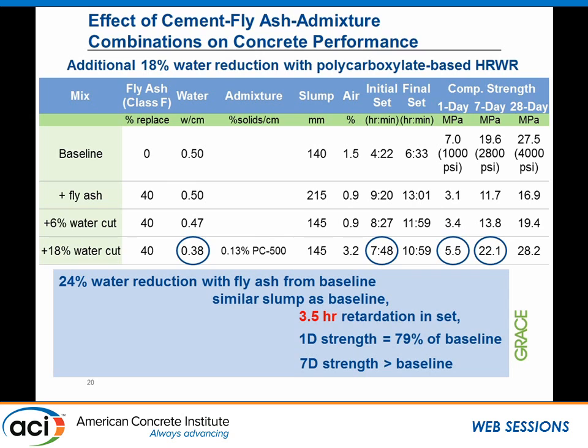So what can we do now, right? Obviously, we can further increase the water reduction. In this case, we use 0.13% of the polycarboxylate 500, which was the best case I showed you earlier. We can realize an 18% water reduction, so a total from baseline of 24% reduction. We gain back some set time, but still it's a 3.5-hour retardation.